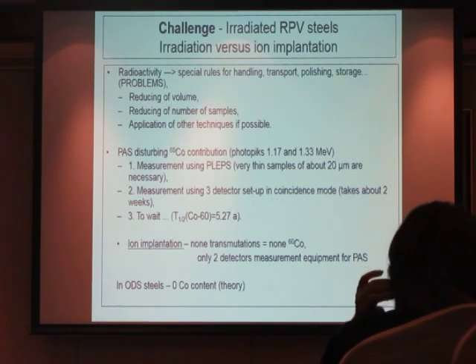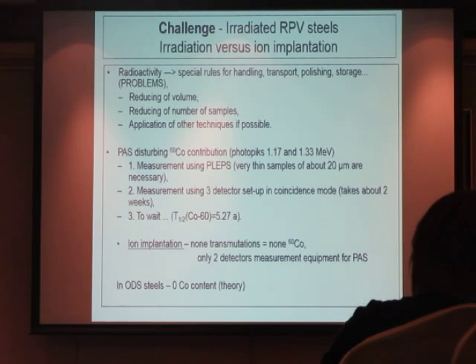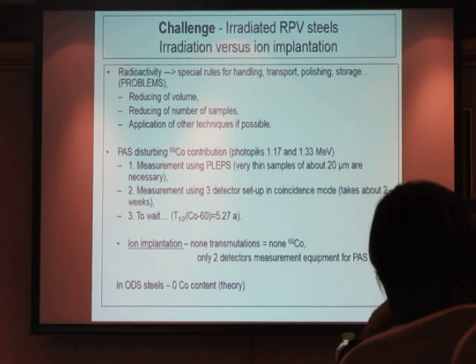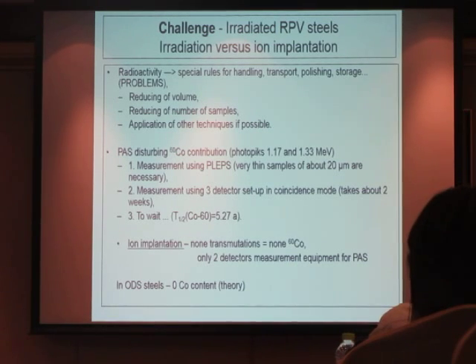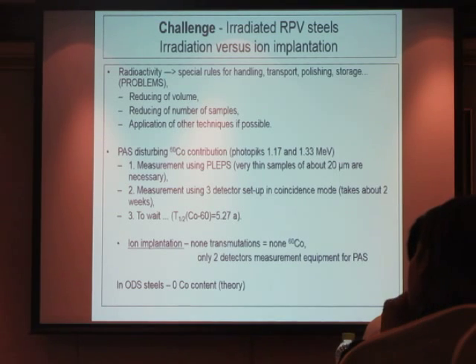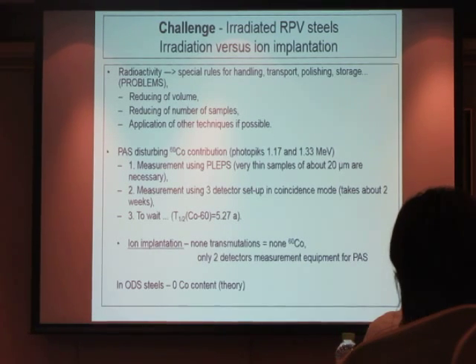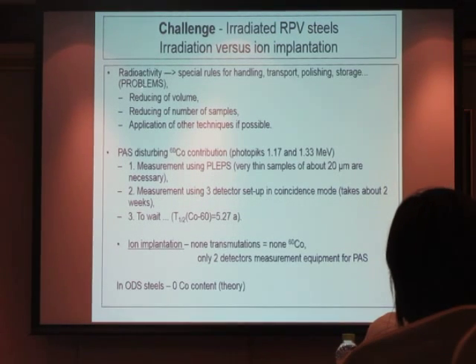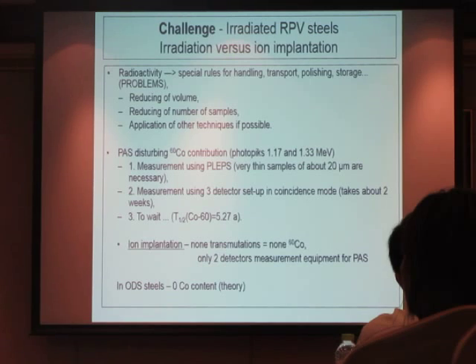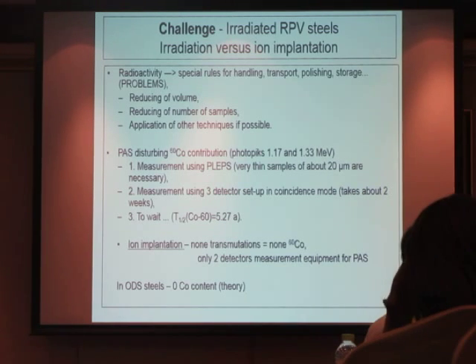The big challenge for the study of irradiated reactor pressure vessel steel is cobalt-60. Therefore, you have to change technique from a 2-detector setup to a 3 or more detector setup. Another possibility is to use a positron beam. Both approaches have been done in the last 20 years. If you have the cobalt side, you can reduce the volume of the specimen. But finally, you need at least a 5 by 5 millimeter specimen to make some measurement. It's not possible to reduce it too much. You can reduce the number of samples, but you need at least 3 points to make a curve. It's also limited. Or application of other techniques, if possible.